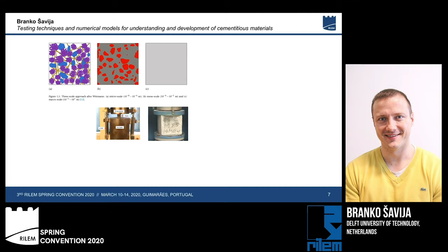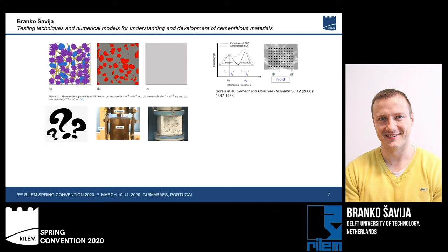Now, we actually want to go one scale lower in order to understand this. So the scale of hardened cement paste, where we can distinguish between cement hydrates, anhydrous particles, capillary porosity, and so on. And how do we go about doing experiments at this scale? It turns out that for about 15 years, people have done a lot of experiments to understand the elastic properties of hydration phases in hydrated cement paste.